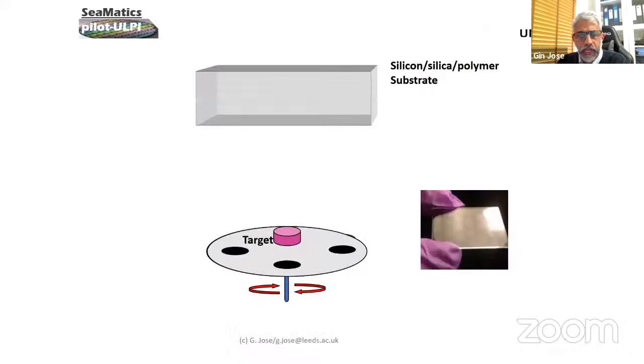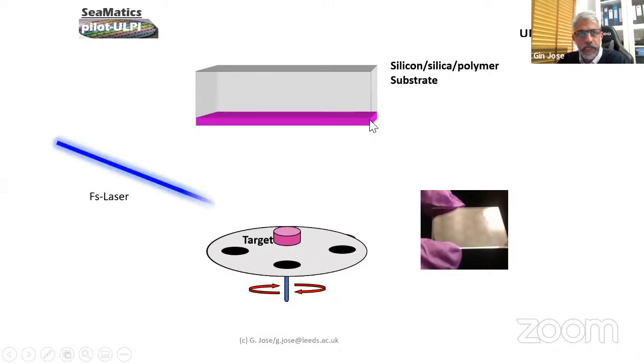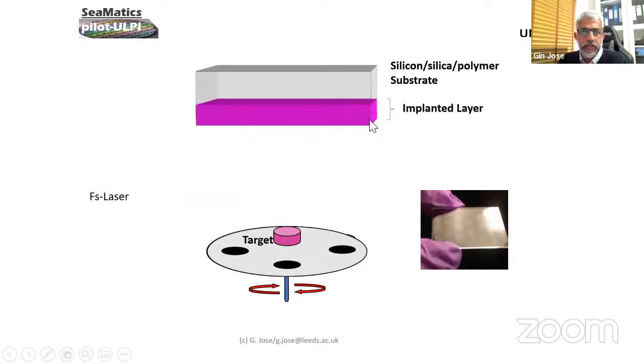So now we look at the typical deposition process. I said the material will be ablated and deposited on a substrate. But here what we are looking at is the ablated materials getting into the substrate, so that you basically modify the substrate layer by layer, deeper into the substrate. By modifying, you mean that we can change the refractive index of the material, and we can also change the doping within. We can bring in dopants like the lanthanides, the rare earths that we discussed in the previous talks.